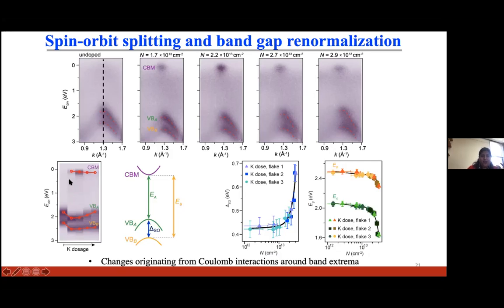After the first dosage, we observe a rigid band shift to higher binding energy. The conduction band shifts to a higher binding energy, and we can see it now. Both of these branches, the upper branch and the lower branch, which I'm labeling as VBA and VBB, shift to a higher binding energy as expected. But interestingly, when we dope more, the conduction band keeps shifting to a higher binding energy, but these two branches of the valence band start shifting to a lower binding energy.